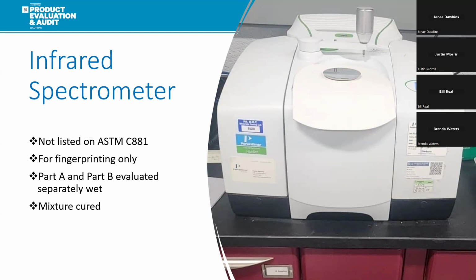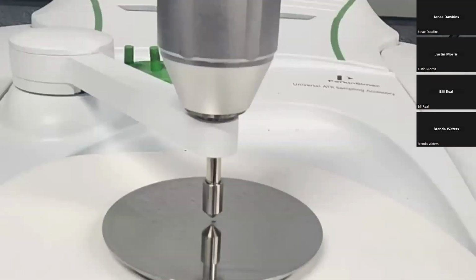Part A and Part B are evaluated separately, and they're evaluated wet. Then you have a mixed cure that is evaluated just as the solid. And this is just a close-up of what you're testing. There's a tiny, tiny little hole in the middle of the metal plate. That's how small the sample is that you're testing. You don't need a whole lot of material. You're just going to shave a little bit off of the product or the dog bone, put it into your IR, and obtain a scan.